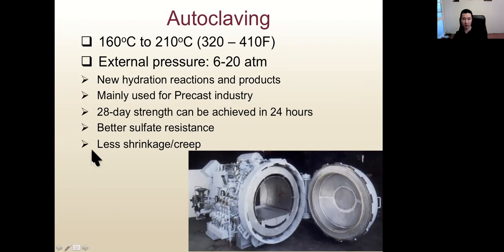But the strength gaining speed is very high. We can achieve 28-day strength normally in 24 hours. The concrete will have better sulfate resistance, less shrinkage, less creep, and better performance overall. But again, this is only in the precast plant, and the size of the concrete cannot be very large because we need to fit it into this autoclaving machine.